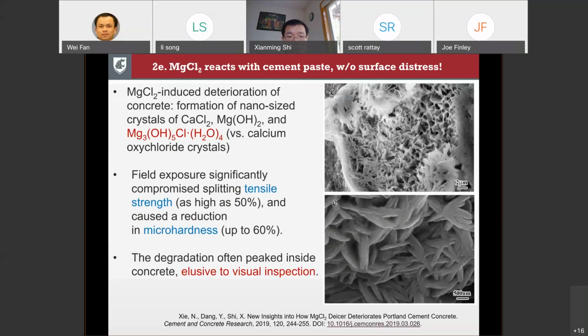What's even more alarming is that this type of degradation often peaks inside the concrete. So on the surface, you are not seeing any sort of surface distress. Typically, there's no cracking or permanent deformation. So in other words, if a bridge engineer goes out there every 2 years, inspects the bridge deck, they rate the bridge deck 9 out of 10. But when you take a core, sometimes you're losing half of the strength. That's very concerning.